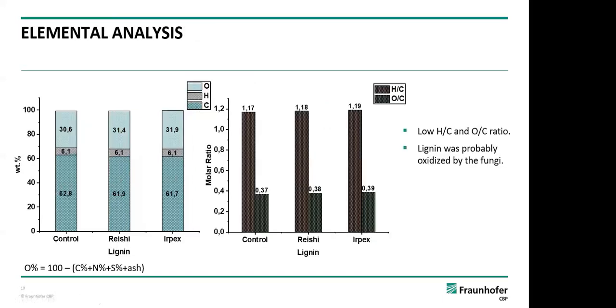In these slides, we did the elemental analysis for the recovered lignin to know the hydrogen to carbon ratios and oxygen to carbon ratios. And we see that we got lower ratios. And this is maybe due to the lignin being oxidized by the fungi.